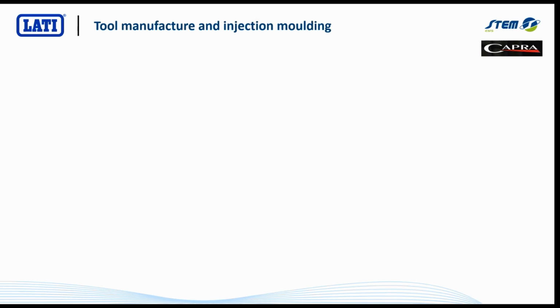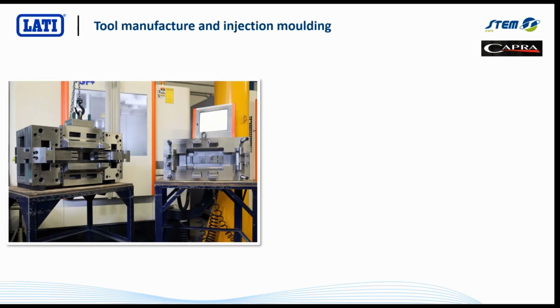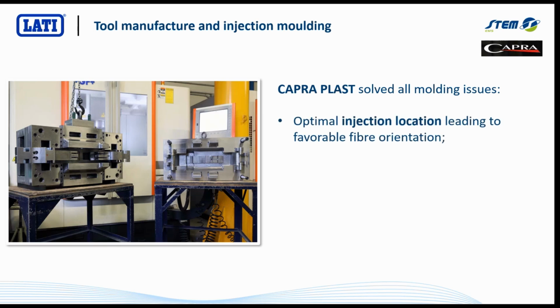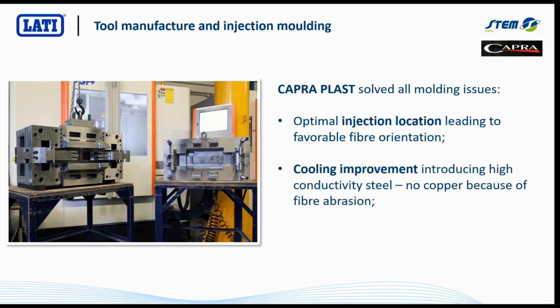And at this point, it's worth saying that this is where it really, really helps to work with a specialist technical molder who's got the experience at working with high performance materials like this. So at this point, really, Capra Plast really took over, and using the information that we provided to them from the analysis, they were able to make a number of modifications to get a part that would actually come out looking like we wanted it to. So that involved optimizing injection molding locations to get a better fiber orientation in the part. And the other big thing it involved was designing improved cooling channels to avoid those big fluctuations in surface temperature that we saw on the previous slide.